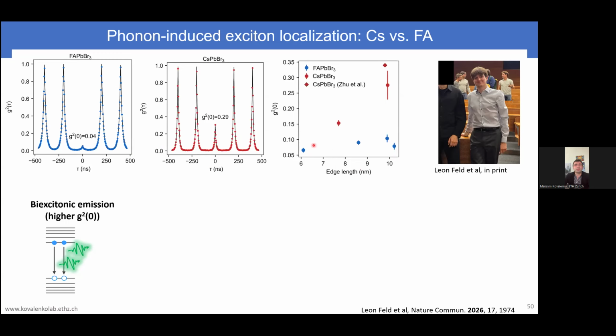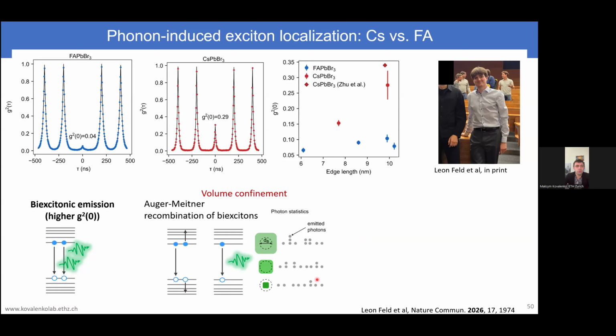The reason why it's unusual is because normally the larger the quantum dot, the more likely you get contributions from biexciton at room temperature. And you cannot separate them because it's all mixed in one emission band. And because a larger dot can afford basically a longer living biexcitons. And the usual way to keep biexcitonic emission, so this is biexciton generating two photons, the usual way to get rid of biexciton is just to keep the dots very small.